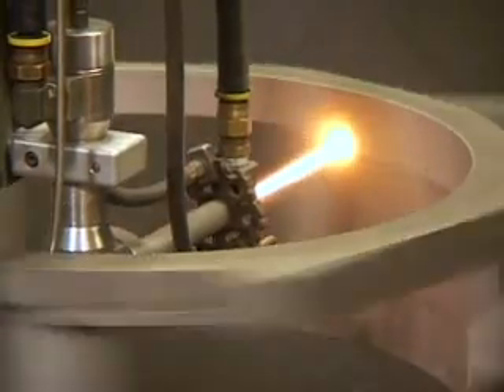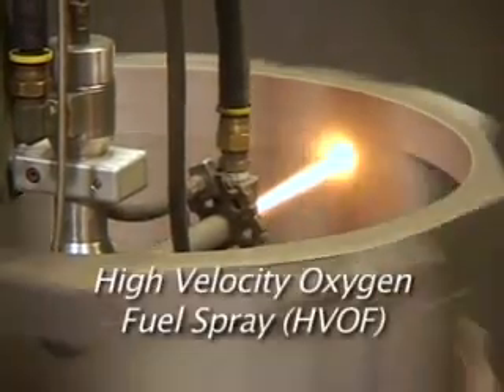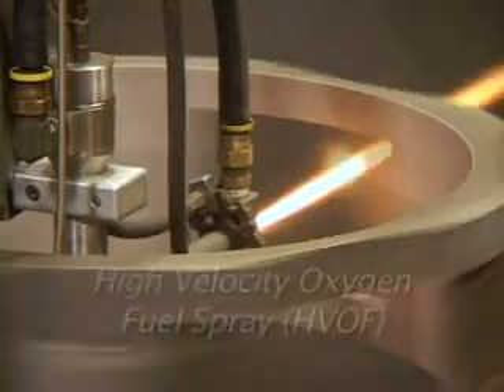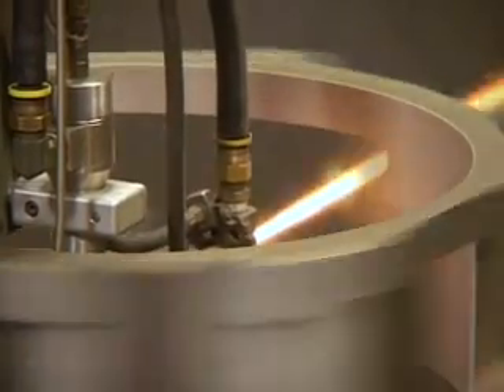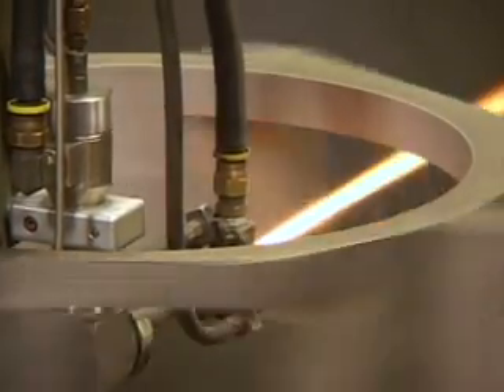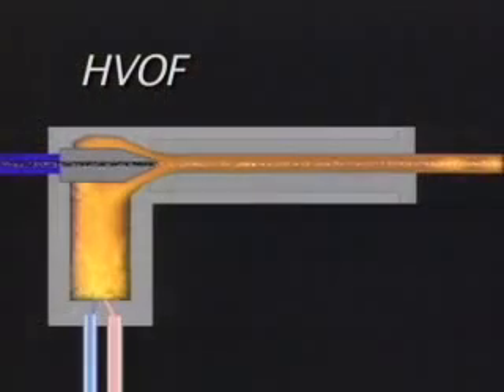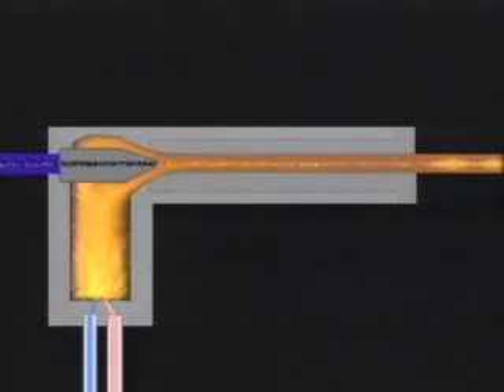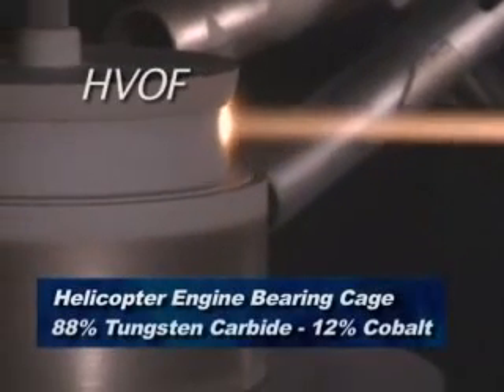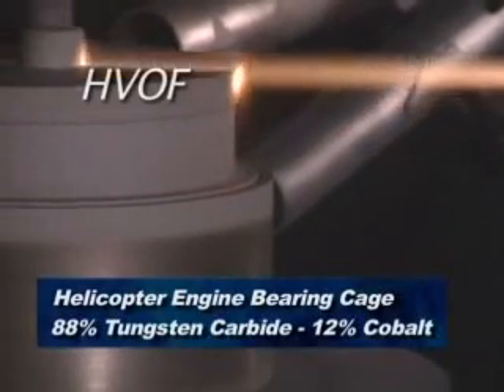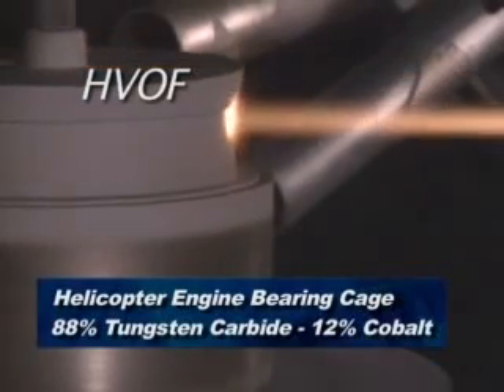The newest of the thermal-sprayed coating technologies, high-velocity oxygen fuel spray, achieves even greater coating densities than are possible with plasma spray. With HVOF, the coating material is injected axially into the nozzle and protected from atmospheric oxygen by the enveloping combustion stream. The material is then propelled at a velocity in excess of Mach 2 onto the substrate, where interparticle bonding and a sintering reaction result in a dense, uniform coating.